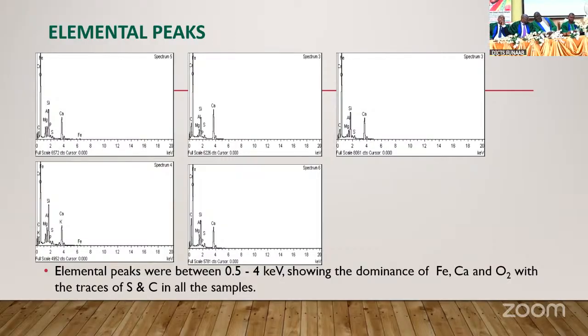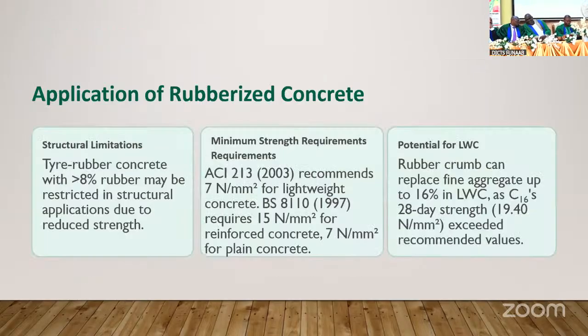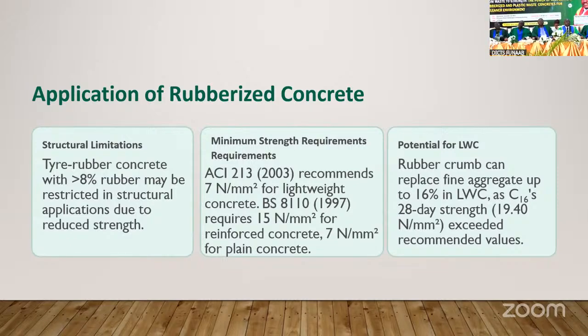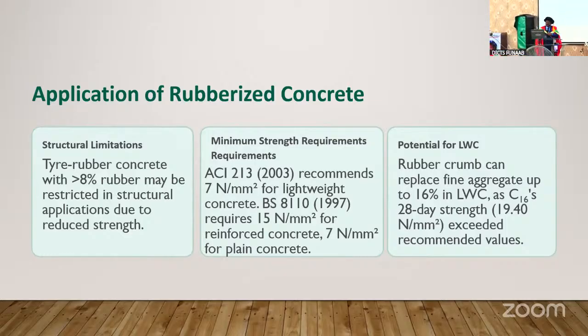Now, application of rubberized concrete. What is the code saying about this? For structural limitation, tire rubber concrete with greater than 8% rubber may be restricted in structural application due to reduced strength. But according to ACI 213, that's American Concrete Institute 213, it's recommended that 7 newtons per mm square should be good for lightweight concrete, and BS 8110, which we use in Nigeria for our design code, requires 15 newtons per mm square for reinforced concrete and 7 newtons per mm square for plain concrete.